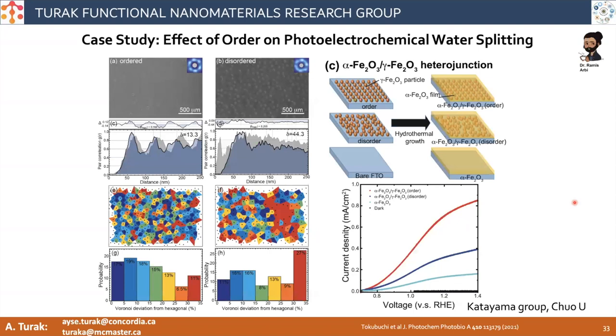And I can give two examples. One is going back to that water splitting study that we did before, where we were able to see that for similar sized particles with similar dispersions, just by changing their order on the surface, we could boost the conversion efficiency for water splitting by about 50% or so. We were doing this in collaboration with some colleagues in Japan, where they were able to measure the current density when we have highly ordered systems versus ones that were disordered or just without any nanoparticles at all. So we were able to see this influence of pure order on the structure.